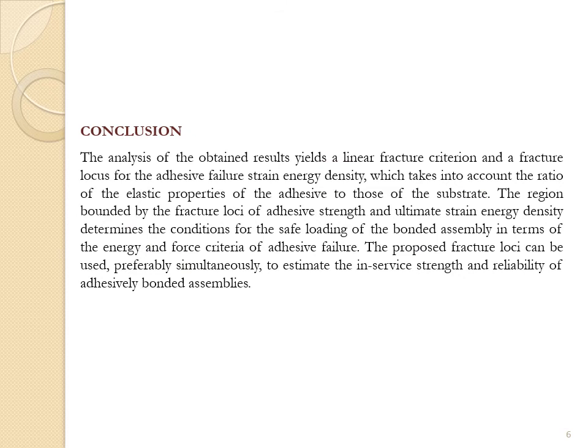The analysis of the obtained results yields a linear fracture criterion and a fracture locus for the adhesive failure strain energy density, which takes into account the ratio of the elastic properties of the adhesive to those of the substrate. The region bounded by the fracture loci of adhesive strength and ultimate strain energy density determines the conditions for the safe loading of the bonded assembly in terms of the energy and force criteria of adhesive failure. The proposed fracture loci can preferably be used simultaneously to estimate the in-service strength and reliability of adhesively bonded assemblies.